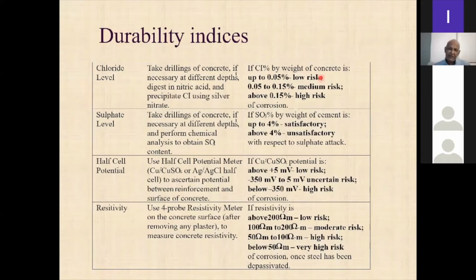Let us say a structure has been close to the coast for about 25-30 years. You can get at different depths what the chloride level is, right? So up to 0.05% by weight of concrete is low risk, greater than 0.15% is high risk. And these are the values for sulfate, right? So this is the way that